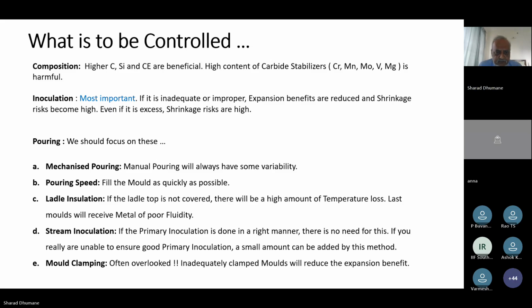Ladle insulation. What I mean here is insulation from the top, because that is the area where your temperature loss is highest. If you are controlling temperature loss from the top, then you are ensuring that your molds get poured at a consistent temperature and consistent fluidity, because if fluidity drops, then you again run into risks of shrinkage and other defects. So ladle insulation is another. I think most of the foundries are doing it now, but I am just highlighting it here because it is very, very relevant.